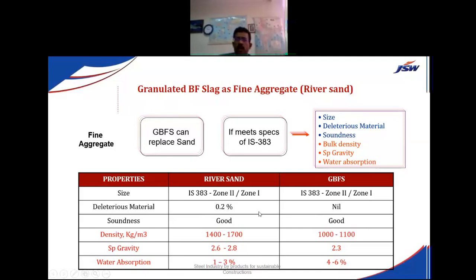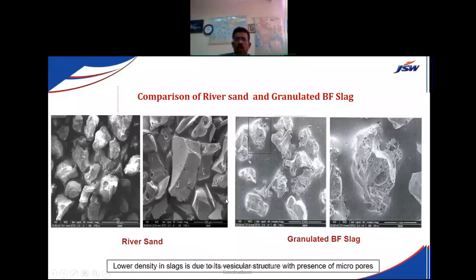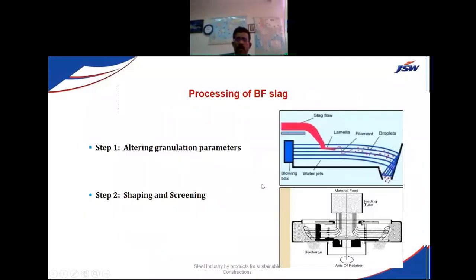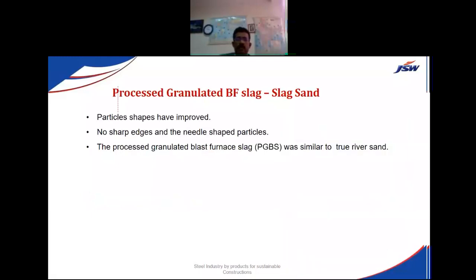So to remove the oversized particles and to fix the bulk density and specific gravity, we used a manufacturing process. As I told you, it is the first of its kind in the country. We converted the granulated blast furnace slag into processed granulated blast furnace slag, which meets the requirement of our IS standard as well as the specifications of river sand. The processed one has the particle shape completely improved, with no sharp edges. The processed granulated blast furnace slag is similar to river sand.